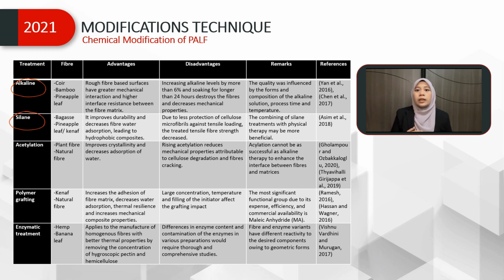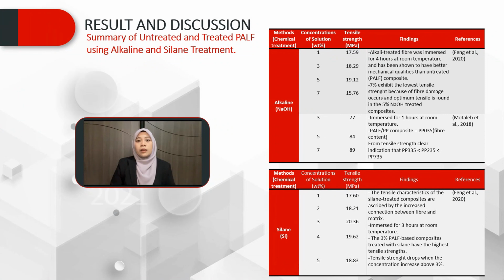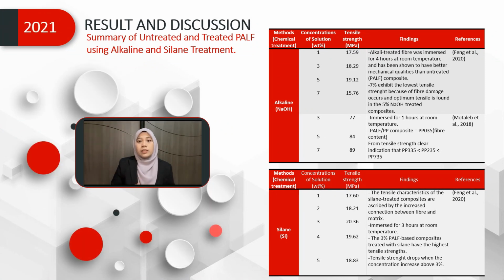Silane, including 3-aminopropyltrimethoxysilane, APS, is commonly used as a coupling agent to reduce the amount of hydroxyl groups adsorbed onto the fiber material surface. The variation of parameters such as the concentration and type of solution treatment were discussed respectively, and the tensile strength increased with the increase of solution concentration.